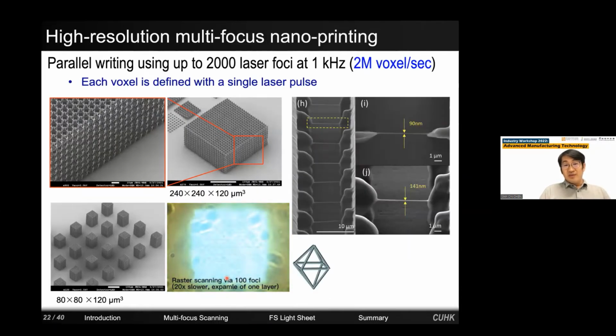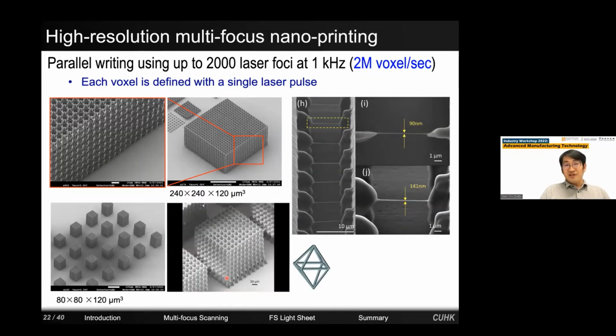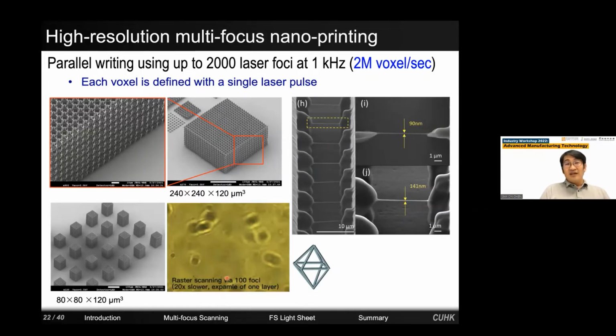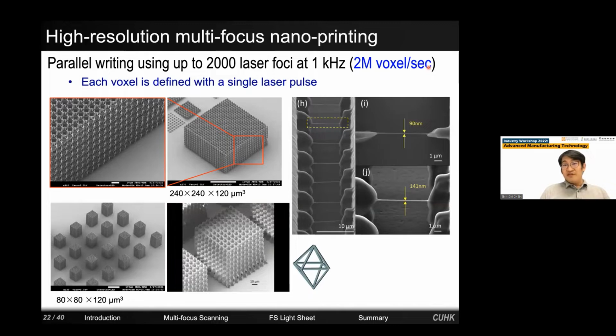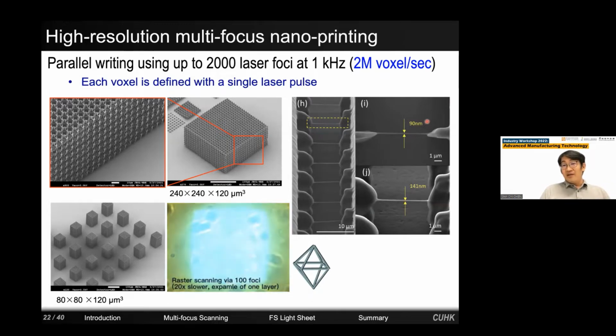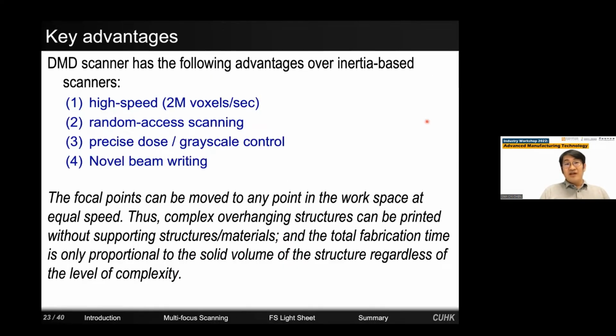In the recent 1 or 2 years, we further enhanced the performance of the system by using a regenerative laser amplifier. And nowadays, we can use up to 2,000 laser foci, achieving a 2 million voxel per second writing speed and breaking the record of resolution, down to 90 nanometers. So to quickly summarize, we use a digital micromirror device to perform high-speed multi-focus scanning, and each focus is individually programmable and can perform random access scanning. In fact, each focus can also carry different laser power, so they achieve grayscale control. A very capable system to create 3-dimensional structures.